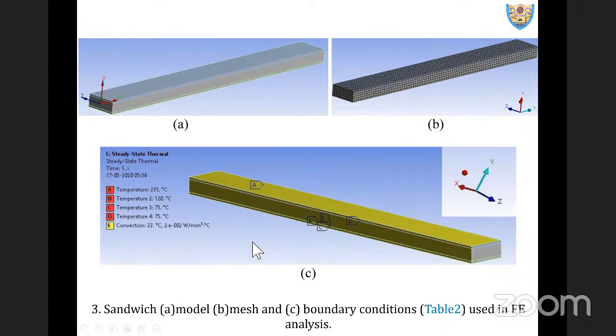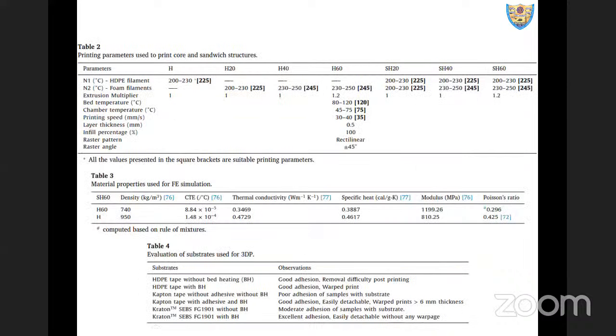And before that, we did the exercise of finite element simulation using ANSYS. As all of us know, 3D printing involves complex heat and mass transfer phenomena that affect the dimensional accuracy of the final part. So we carried out a thermomechanical FE simulation using ANSYS. We fed the properties of skin and core independently. We defined the elements at the interface, merged the nodes at the interface, and followed the regular procedure laid down for analyzing a multi-material system in ANSYS. And then we found out the temperature profile, which I'll show you later.